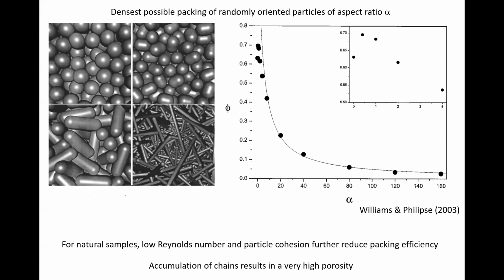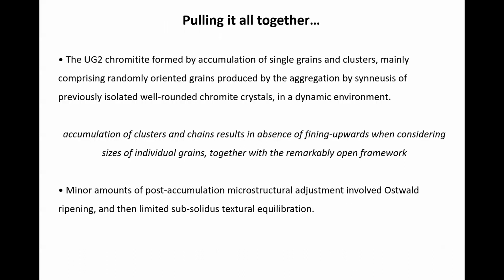We're going to have low Reynolds number in the magmatic situation. We've got particle cohesion. We don't have nice thin rods like this model here. So it's going to be even more sensitive to shape. So the accumulation of chains or random clusters is the way to get this very, very high porosity.